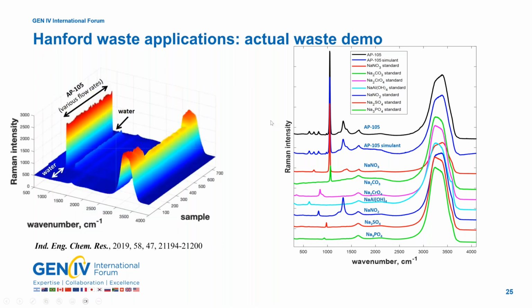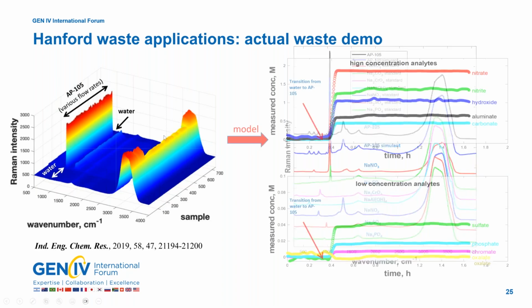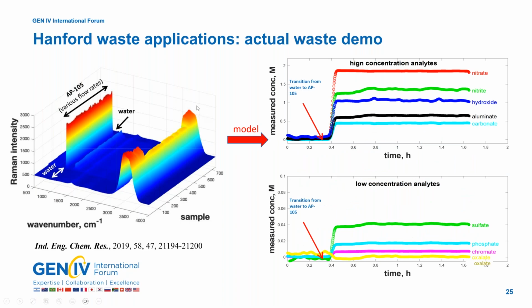The spectra of the AP105 waste is shown here as a function of sample number, which is essentially a time axis. We have the wave number, so we can see the water manifold here, or the hydroxide manifold here. We see the nitrate band over here. So we start the process where we have water initially in the cuvette flow loop. Then we transition over to AP105 waste and measure that. Now we can go ahead and then use our chemometric models and process this spectral data and turn that into concentration data based on the model that we employed.